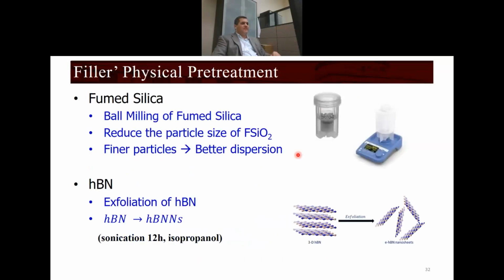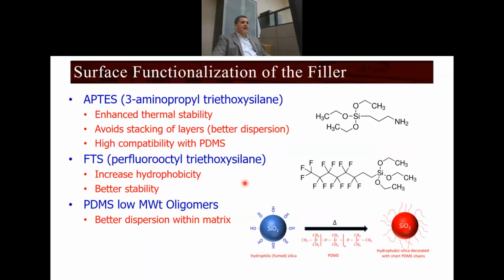So the physical treatment, as I mentioned, is ball milling to reduce the particle size and to get a better dispersion of the filler within the PDMS matrix. And the exfoliation will do the same thing too, just trying to understand if the exfoliation will have an effect in this kind of application. And this is the chemical treatment using 3-aminopropyl triethoxysilane (APTES) to enhance the thermal stability and dispersion, and also this is very much compatible. Based on the literature, it's highly compatible with PDMS. Many people are using it already.